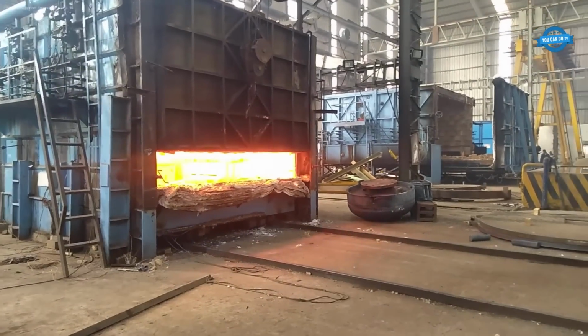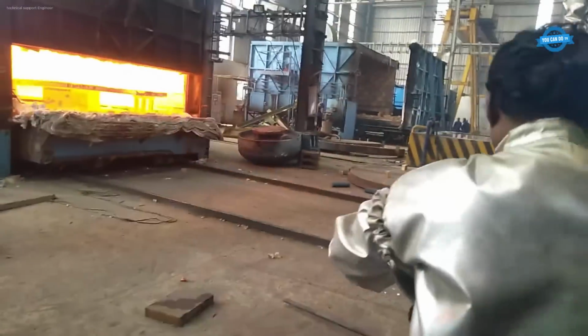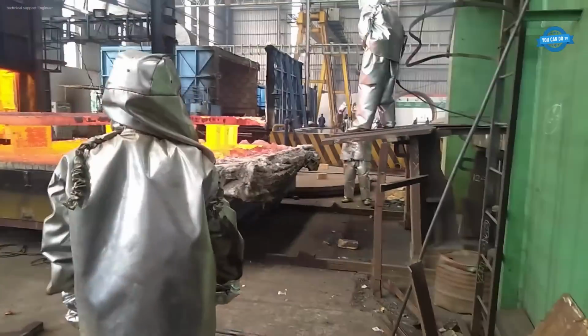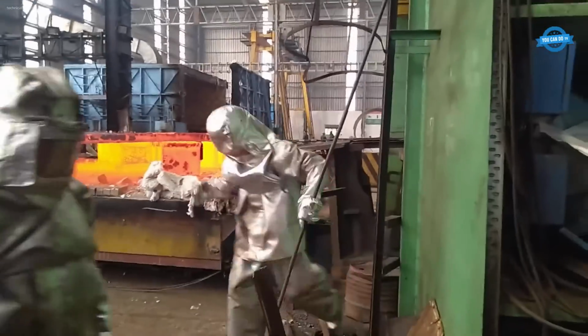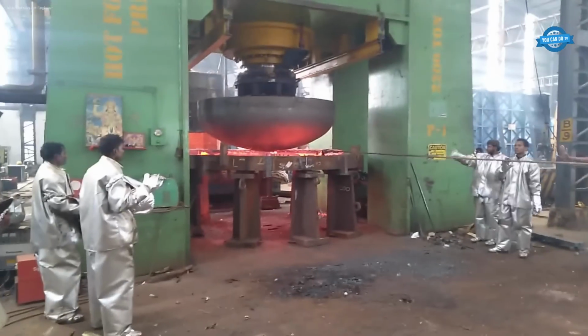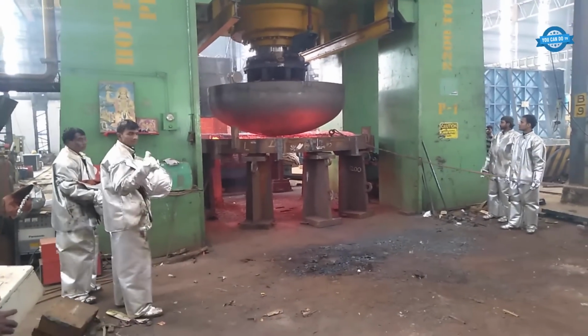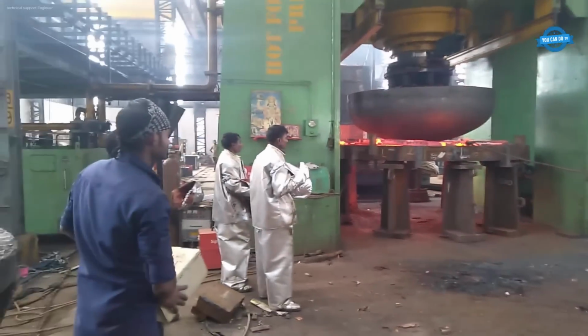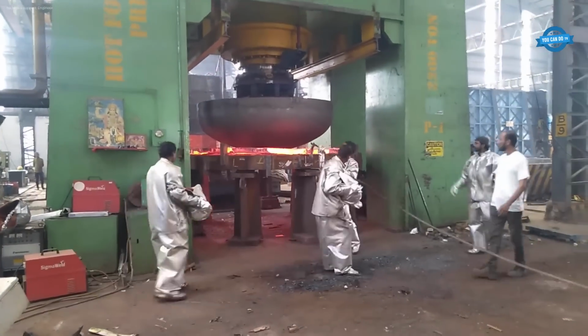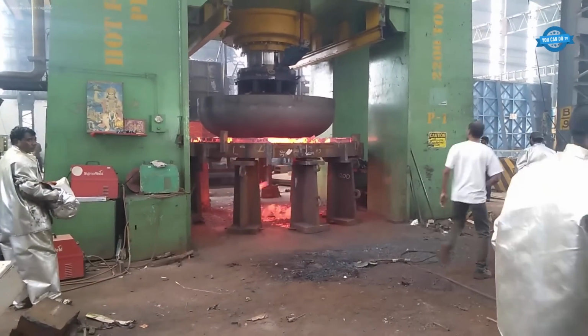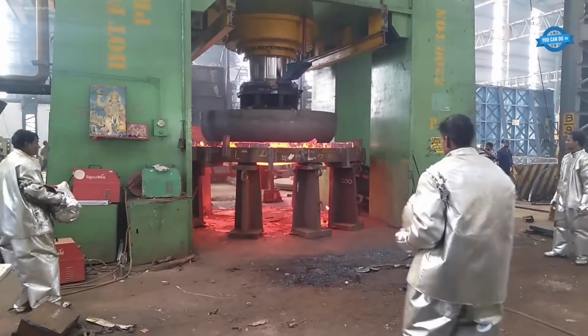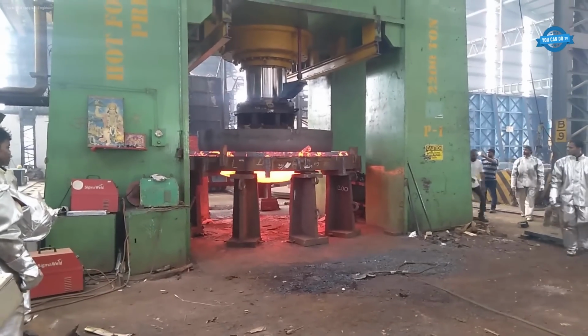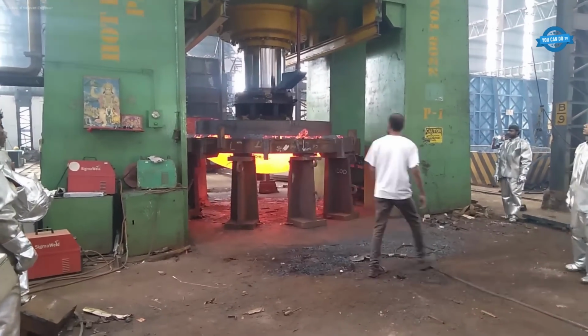Under intense heat and precision force, flat steel plates are transformed into strong, curved, dished ends, vital components for pressure vessels. In hot forming, the steel is heated to around 900 to 1000 degrees Celsius, increasing ductility for easier shaping. Hydraulic or spinning presses then mold the plate into torispherical, ellipsoidal, or hemispherical forms.